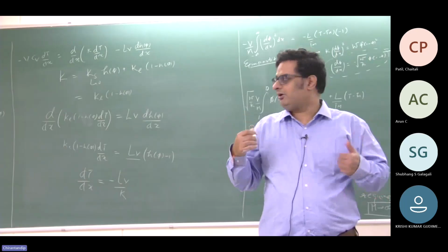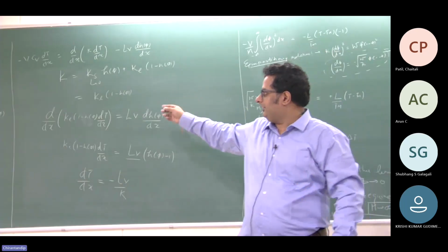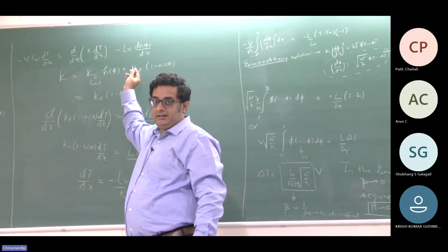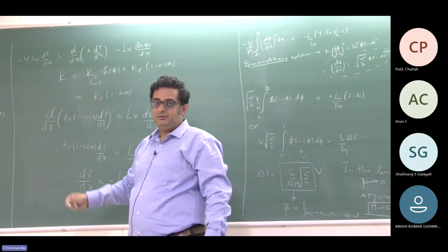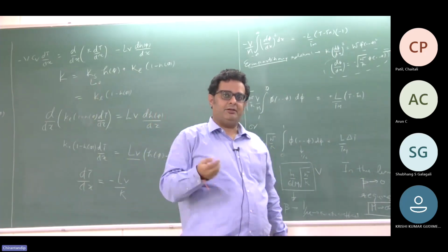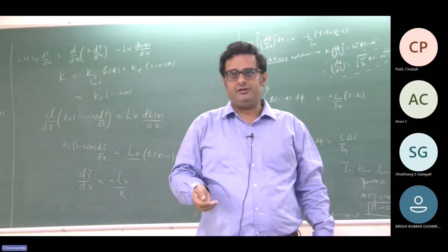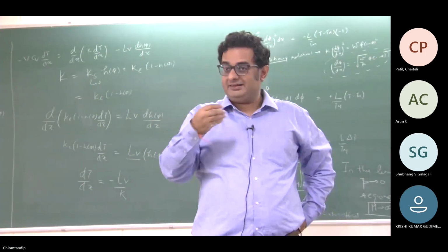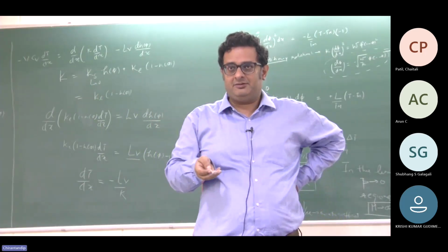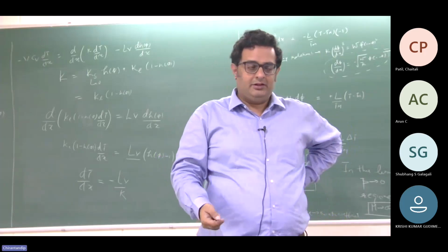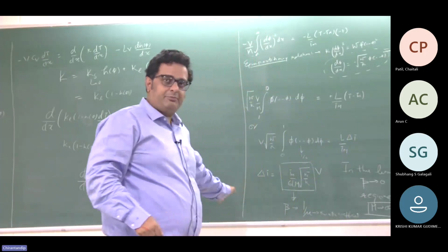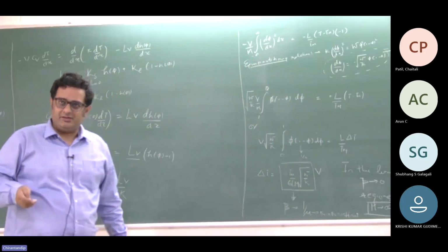Right? But here, because of the way that your A is not uniform and it is biased towards one side, you land up in a situation where you have a jump in the temperature, a jump in the chemical potential. That is what you have to see in trapping. This is essentially what is related between heat trapping over here and solute trapping in this.